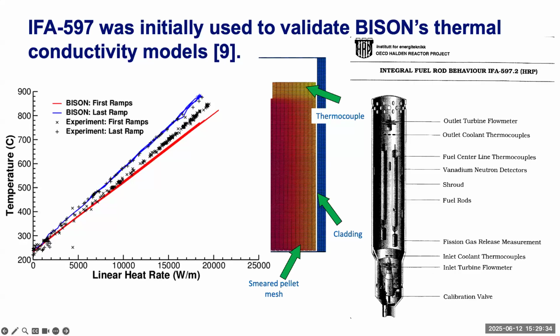That is going to influence fission gas release to a certain extent because we're looking at fuel that already has significant burnup, likely already has these pathways or tunnels for the gases to escape. And looking at the different fuel geometry, because it's going into a smaller fuel rod, we likely will see more fission gas release. Hopefully that answers that question.